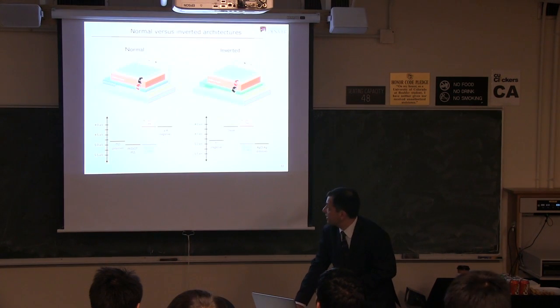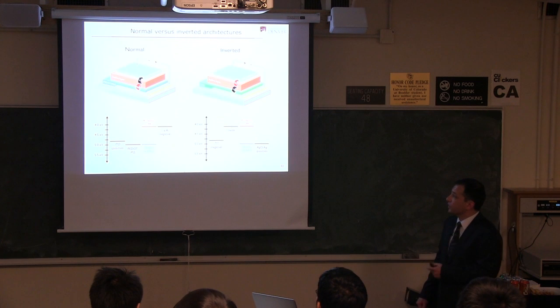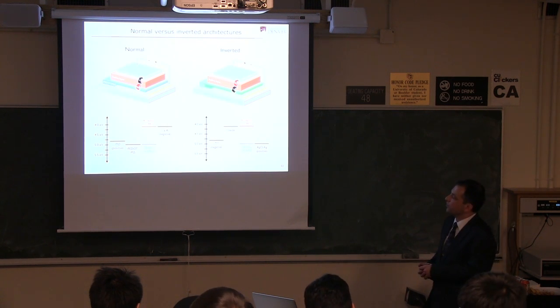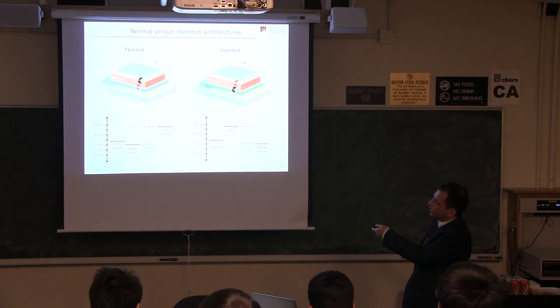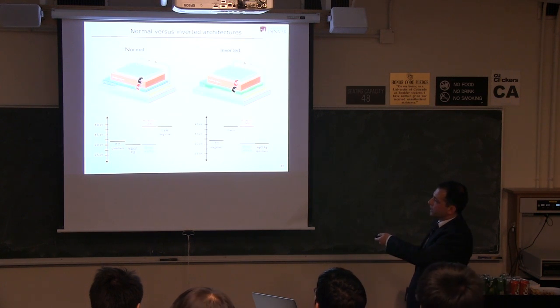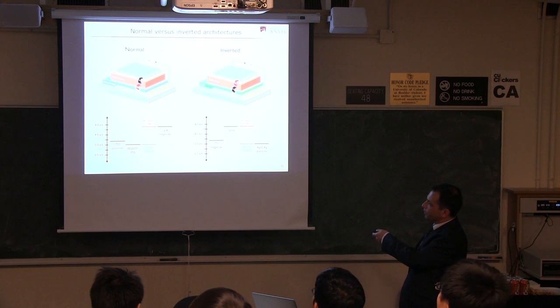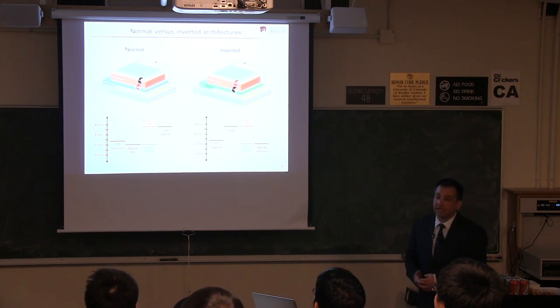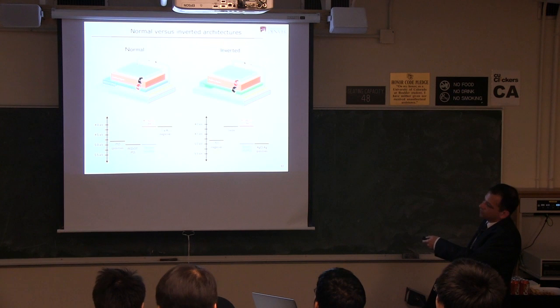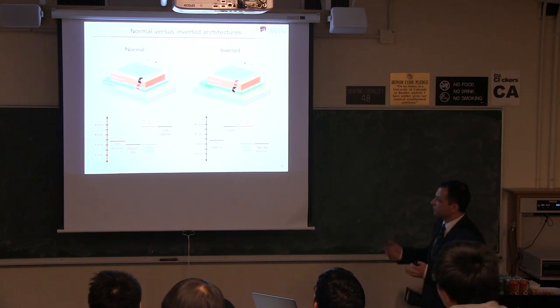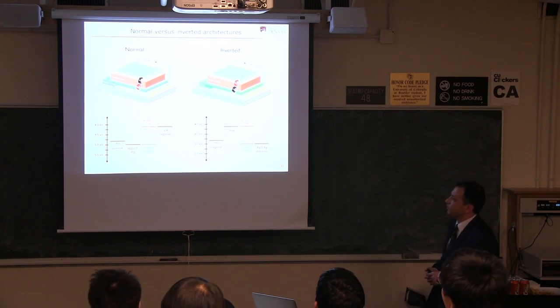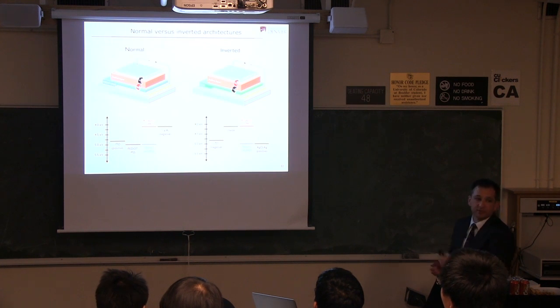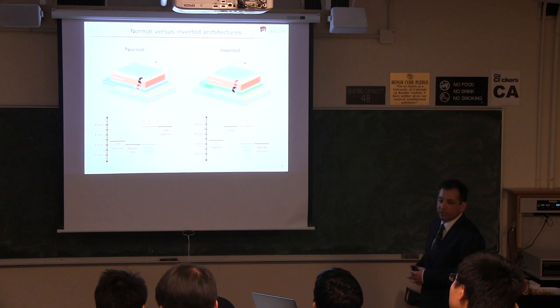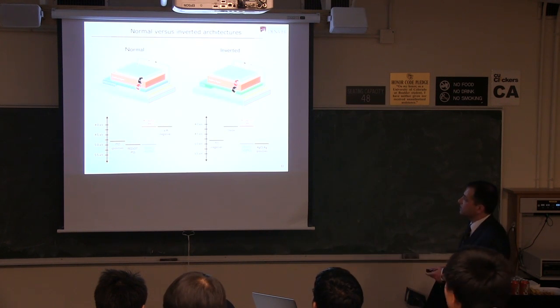Okay, just want to mention about device architecture. So you can make these in two different geometries where you use a conducting polymer as one of the electrodes, which has a fairly high work function. And that means on the top, you have to use a fairly low work function metal, like calcium. These devices work very well, and most labs will make these devices as kind of a first try. But you can see a problem of using calcium as an electrode. It's very oxygen sensitive. So to bring it outside in the environment, we need to encapsulate it quite extensively.